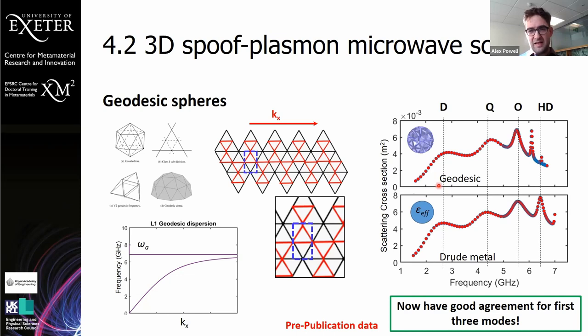But this is a pretty convincing demonstration of replicating surface waves in localized surface plasmon-like behavior for the microwave. And the effective permittivities we see here are, for this structure, around about minus 10, which relates very nicely to what we see in metals, which support plasmons in the optical. So for silver in the optical, the effective permittivity is between about minus 5 and about minus 25. So we're right in that range where we'd expect to see